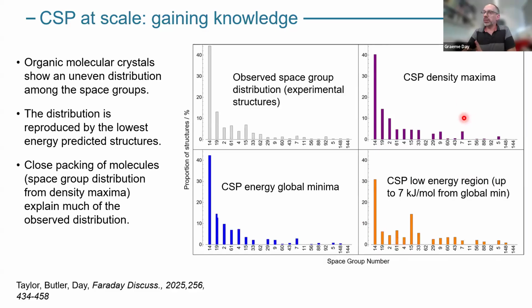If you look at density maxima amongst our crystal structures, so not the lowest energy structure on each landscape, but the highest density structure on each landscape, then you again reproduce observed space group frequencies quite well, which is telling us that a lot of this energetic preference is probably just coming from the fact that certain space groups allow molecules to pack more closely than others, which is something which is understood for quite a long time in terms of organic molecular crystals, but it's nice to see that come out of these landscapes as well.